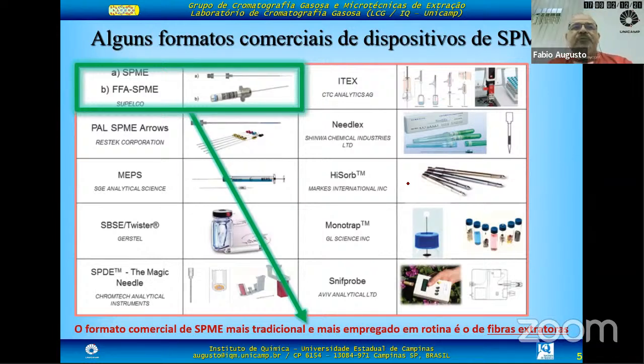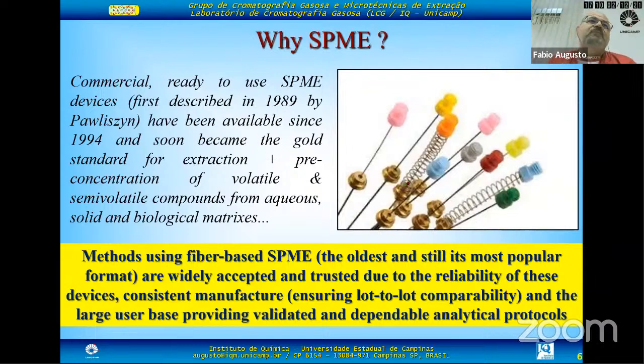is the fiber-based one. Most people associate solid phase microextraction with fiber-based solid phase microextraction, which was initially sold by Supelco, but now there are other companies that make those devices available. You have a thin fused silica fiber, coated with a thin film of absorbent. This is exposed either directly to the sample or its headspace. Well, why use fiber-based SPME? Commercial, ready-to-use solid phase microextraction devices have been around since 1994. They are widely accepted, both by academia and by industry. You even have standard methods based on fiber-based solid phase microextraction devices.